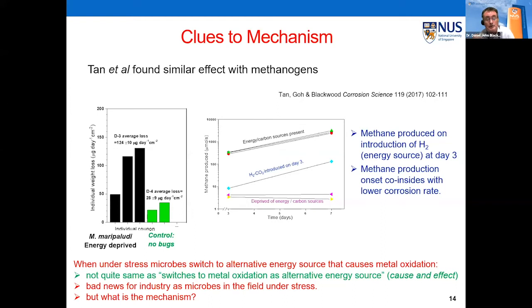They switch to some alternative energy source that causes metal corrosion. However, that's not quite the same as they switch to metal oxidation as an alternative energy source. Okay, there's a slight difference there. They've changed their mechanism, and that causes the corrosion if they're not taking it directly from the metal. This, of course, was always bad news for industry because microbes in the field are under stress. So they're going to be causing more corrosion in industry than they will in your lab.